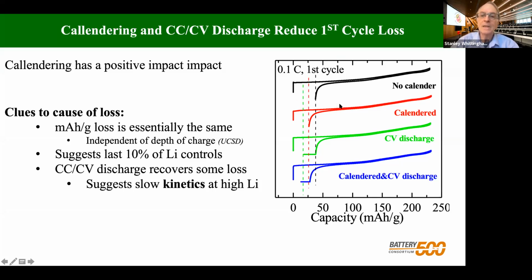If we calendar it, what that means is, after making the electrodes, we put it between two rollers and squash it flat. This is a few tons per square centimeter, a very high pressure. You can see we've got part of it back. So making better contact helps. If we now take the first one and just do this constant voltage discharge, you get quite a lot more of it back. And if we're calendaring and do constant voltage discharge, we get even more back. So all of this suggests that it's slow kinetics.